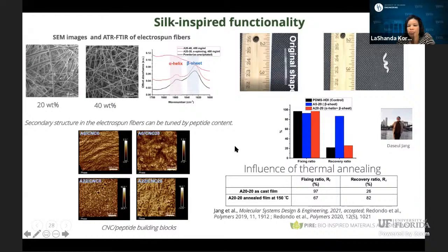And then on the right, this is a recent paper from our group where we've shown that you can have really nice shape memory behavior that is controlled by both the beta sheet content or the alpha helical and beta sheet content in these systems, where there's an influence of the intermolecular or intramolecular interactions on both fixing as well as recovery in these shape memory systems.